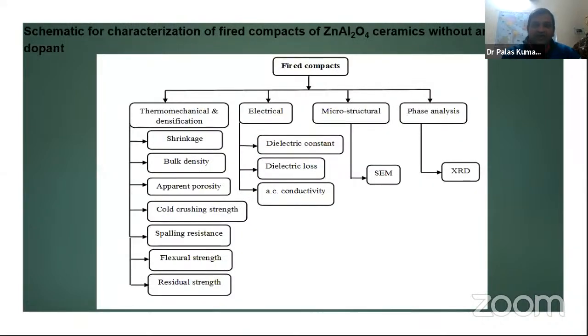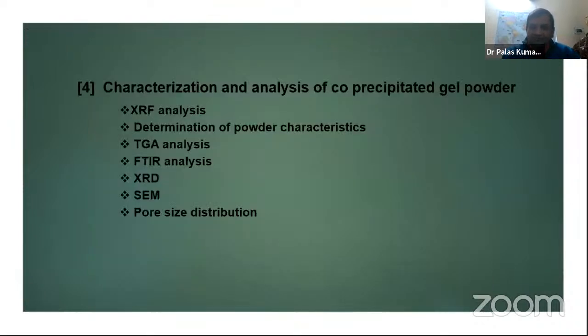So now directly coming to the schematics of the characterization of the fired compact. Before firing, we made the green compact, and the green compact was fired at different temperatures: 1250, 1300, 1350, and 1400. Out of these four, we present here only 1350 degrees because of optical property. I'm coming to the subsequent slides, but the major properties which we studied were the electrical ones, and of course, under physical, the thermomechanical and densification, to compare the effect of the dopant with the existing base material, which was correlated with microstructure and phase assemblage. So coming now to the first stage, the characterization and analysis of the co-precipitated gel powder. Right, there are various characterization techniques we use.